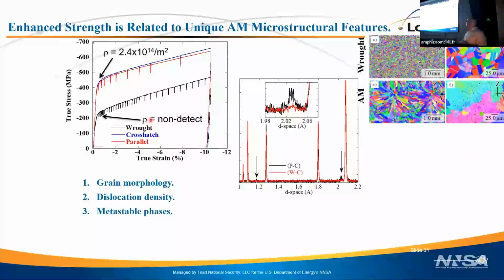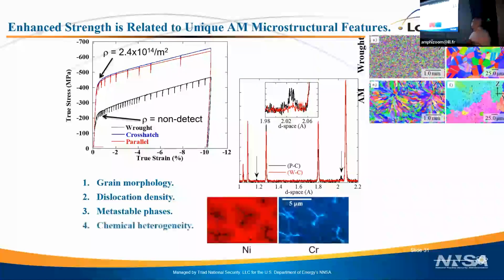Minor phases. You get some ferrite in 304L when you additively manufacture it, when you might not expect to. In the wrought material, and here I'm blowing it up, maybe you have a tiny little bit of ferrite, but in the AM material, you have quite a bit. That could act as a strengthening mechanism. And finally, something that Livermore actually discovered, maybe they didn't discover it, maybe that was too strong a word, is that you get chemical segregation in the material. Again, because it's cooling so fast, the elements don't have time to get to their equilibrium positions. Here it's seen in terms of high areas of chromium. These are almost certainly the ferrite areas, because extra chromium stabilizes the ferrite. So any of these 4 things could result in that strengthening.